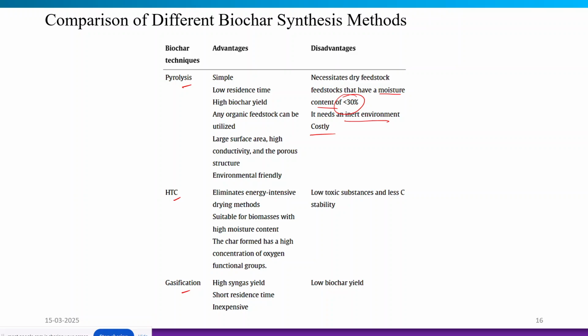While talking about the hydrothermal carbonization process, it is not an energy intensive process because we are eliminating the drying step. Also, any kind of biomass having higher moisture content can be processed through this technique, and we can get a carbonaceous material as a product. Also, the hydrochar produced by the process has a higher concentration of oxygen on the surface, so it has higher reactivity. But the disadvantage is that the carbon stability is lower than the biochar, and there are low toxic substances. In the gasification process, the main disadvantage is that it doesn't yield much biochar. Obviously, it focuses on a higher yield of syngas, shorter residence time, and it is inexpensive.